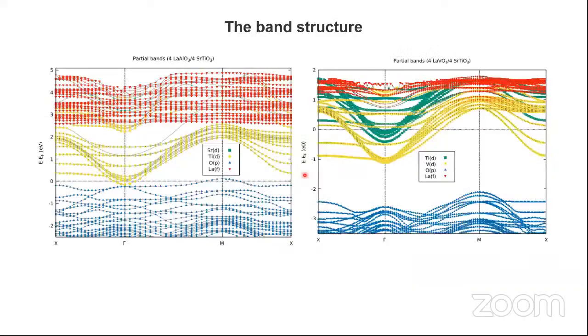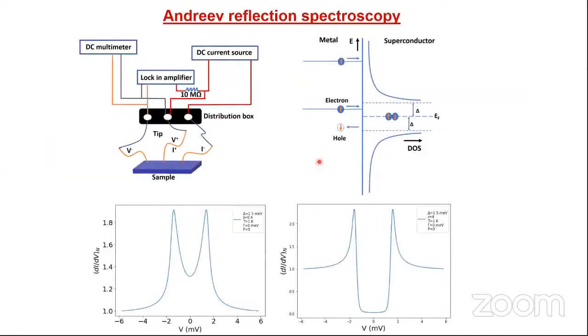We first looked at the band structure that our colleague Tanushree Das did at IISER Bangalore. And what he gave us is that in case of LaOSTO, it's only the titanium band that's crossing the Fermi energy. But in case of LVSTO, we have the titanium band as well as the vanadium band crossing the Fermi surface. Of course, in this case, the strong correlations present in LVO are not considered, but if the vanadium electrons are also taking part in superconductivity, then there is a possibility of unconventional superconductivity. In fact, part of this was spoken about by my student Mona in another talk, but I will go through the details of that once again.